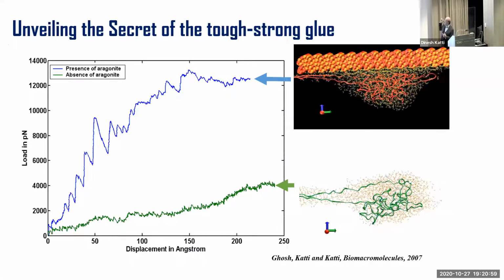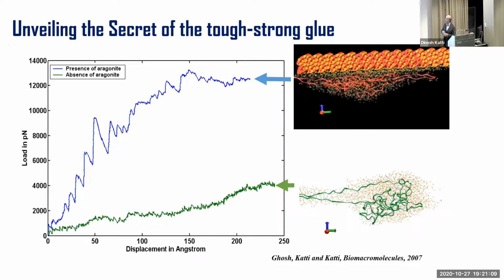After that, the water molecules enter in between the mineral and the protein, and then you no longer see those big peaks. But what you see is that a much larger load is needed to pull the protein in the presence of the mineral. And that makes the protein very stiff, or the organic phase very stiff. At the same time, what you will notice in these plots is that in both cases, the protein stretches by almost the same amount.